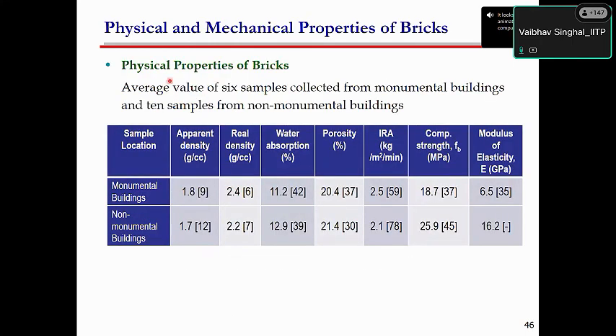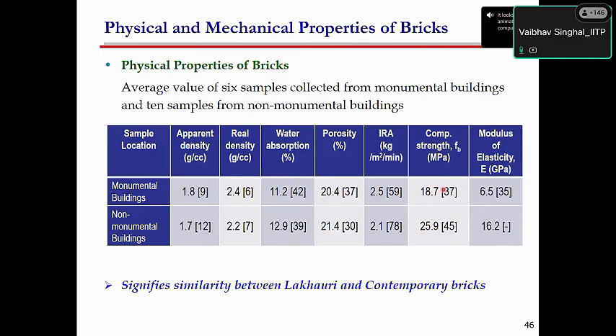So these are the properties of a brick. Brick samples were collected. You can see the density and water absorption were quite good, which shows that the bricks were of good quality, and they had quite significant strength, about 20 MPa, 18 to 25 MPa.